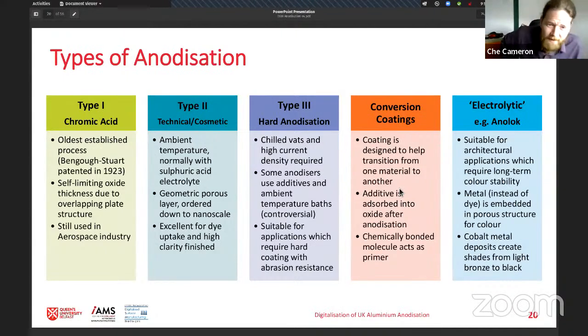So the different types of anodization that we'd see, these 5 different ones I'm going to talk about. We have type 1 chromic acid anodization, and this is the oldest established type, patented in 1923. This has a slightly different oxide structure, which is interesting. Instead of the regular porous structures, it actually kind of collapses on itself and forms almost like a plate armor when you look at it at a microscopic level.